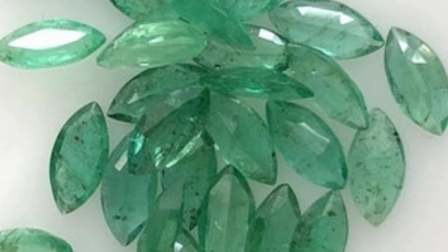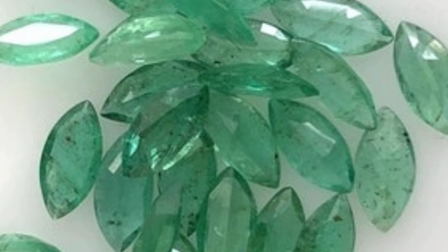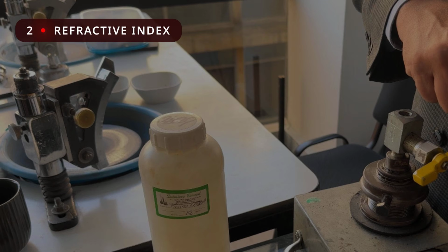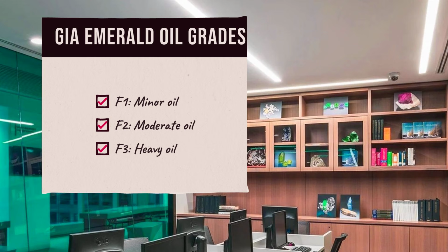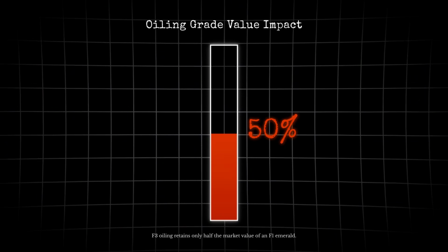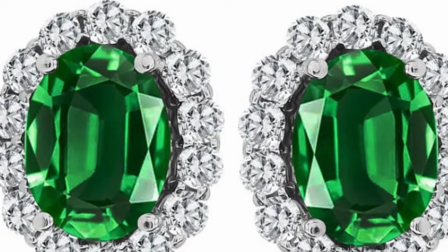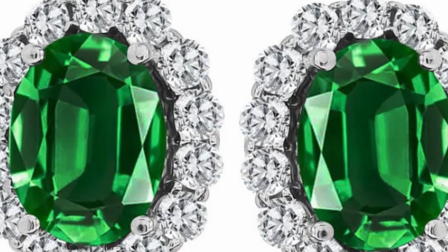Oiled emeralds. If you think you're buying a natural emerald with perfect clarity, you are dreaming. Almost every commercial emerald on Earth is clarity enhanced. Cedar oil has a refractive index of 1.515, close to emerald's 1.577, so it hides the fractures well. The GIA grades oiling as F1 for minor, F2 for moderate, and F3 for significant. F3 oiling drops the value by 50% or more compared to F1.